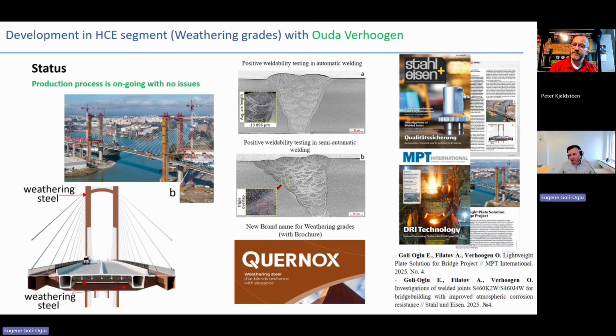And at the same time, by the way, in the recent 5 years, we have also made a lot of developments here, and we were able to decrease carbon equivalent from 0.47 to 0.44, which also improves the welding of the material. And we see that in 2 years, some kind of boom for this kind of material, and we are also almost ready with our own brand in weathering grade called Quernox. I think we are finalizing the special website for this, so it will be available soon.